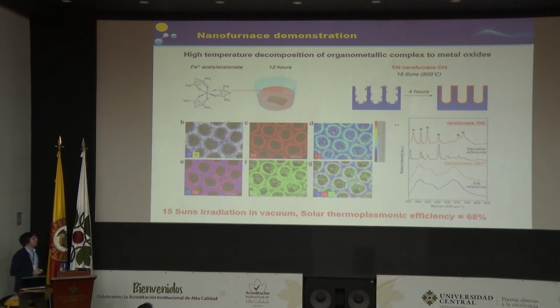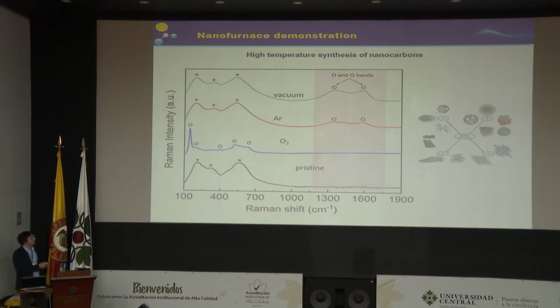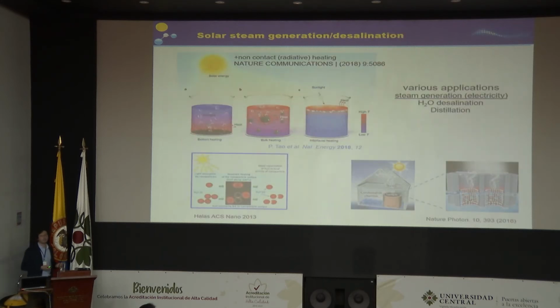You can see here a nice conformal coating of iron oxide on the mouth of these cavities and all along the structures. And by Raman, we saw that this is hematite, so iron oxide again. But really, we can obtain conformal deposition of materials just using the local heating in the walls of the material, where the electric field is concentrated. And we also see that this temperature catalyzes the formation of new carbon bonds.